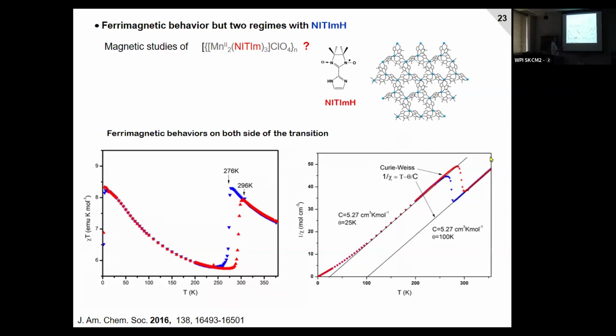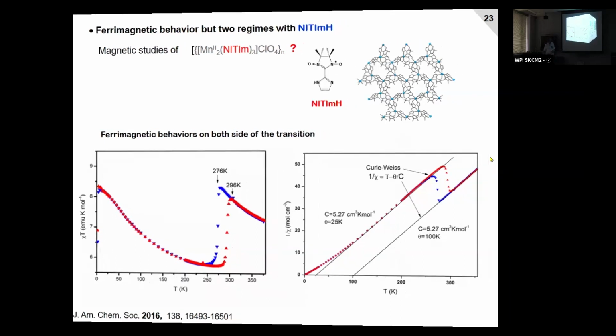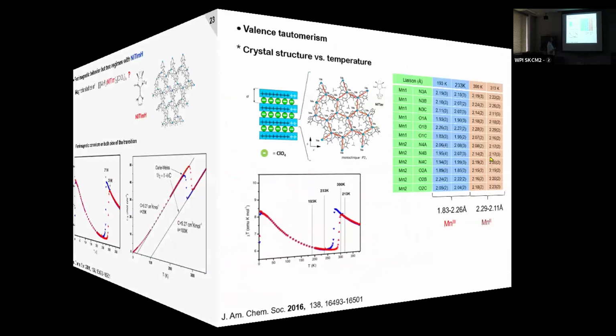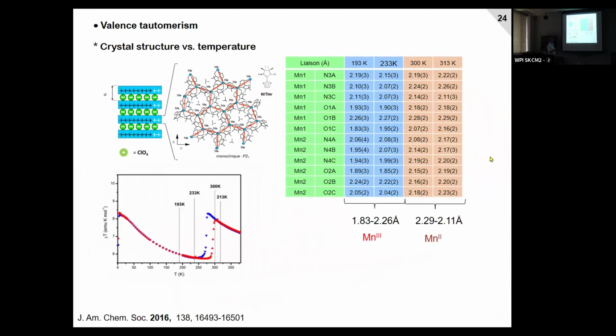We have two Curie-Weiss behaviors, but the slope is on the other side. So it was indicative that we have valence tautomerism, and in fact, to understand if we have valence tautomerism, this means that some of the components change valence state. And we have done the X-ray diffraction on a single crystal more carefully, and we got the structure at 4 temperatures, above the transition, close to the transition, and below the transition.